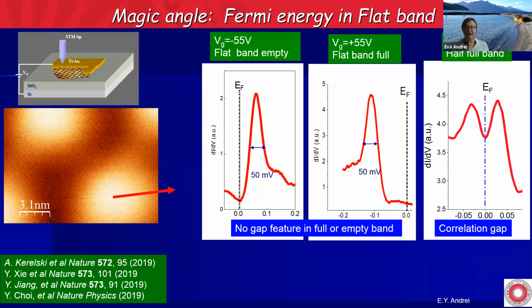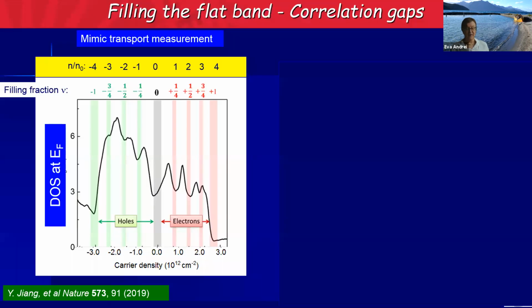Another thing that I wanted to point out: when the Fermi energy is at charge neutrality, the spectral weight is pretty much the same on the full part of the band and the empty part of the band. This changes depending on how many electrons you throw into this flat band. And you can see this right away when we do what we called a pseudo transport measurement. We park the energy of our tip at the Fermi energy, which means 0, and then we change the gate voltage or the carrier density. And you see immediately that you have these beautiful dips at every integer filling.